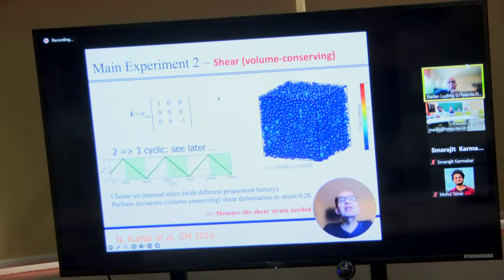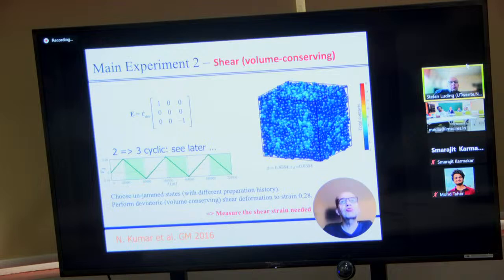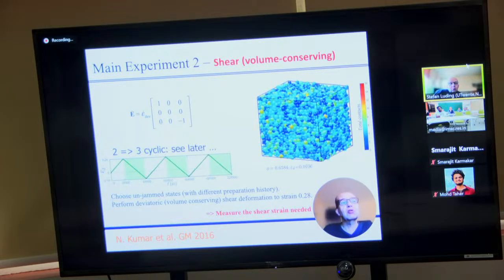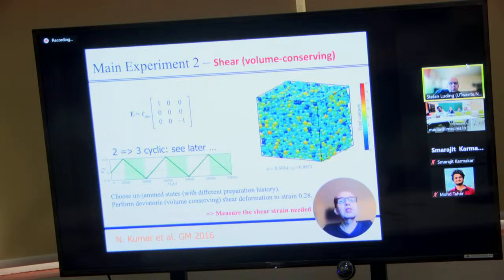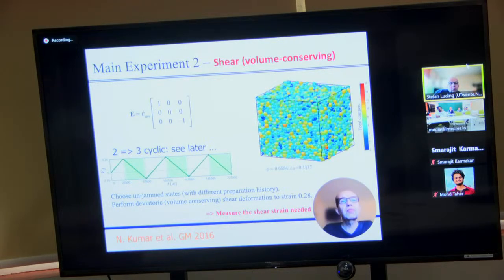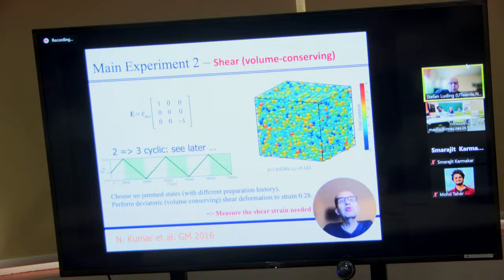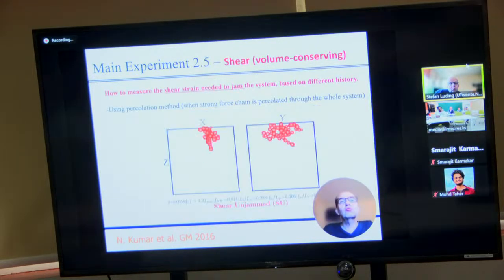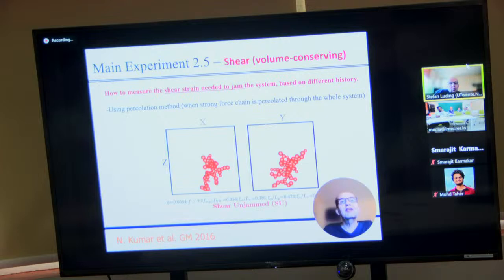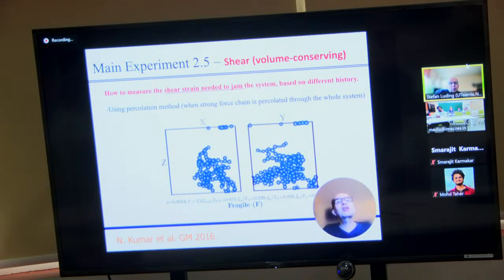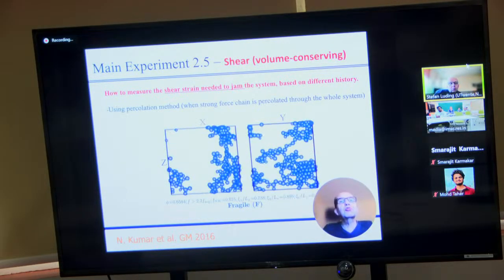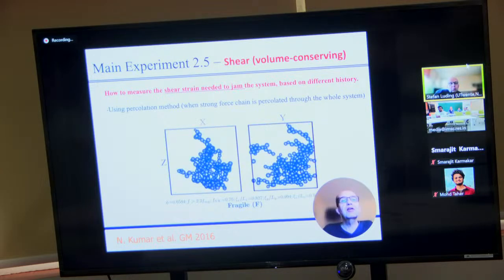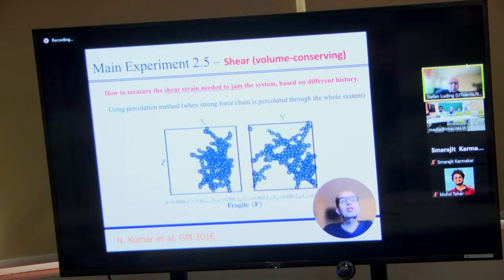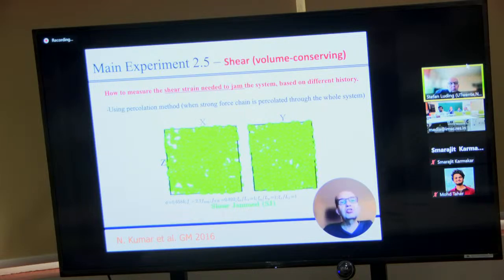Now, this is the animation of such a shear event. It's a special situation. You go from unjammed to jammed in a volume-conserving shear system. And actually, you can do cyclic shearing. You can shear forward, backward, but I won't show too much of this. Okay, now the question is, how much do you have to strain in order to have the system jammed? And the second question is, what is going on inside the force network of the system during shear jamming? So first, the system is unjammed, then it's becoming fragile, and then suddenly it shear jams.